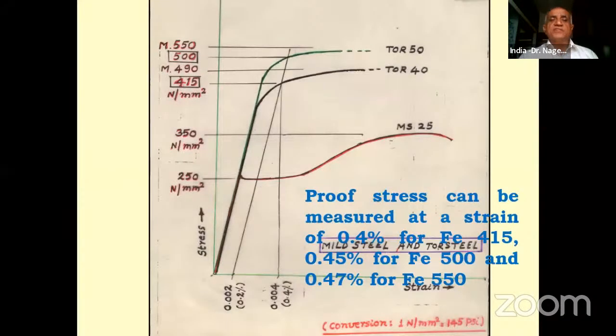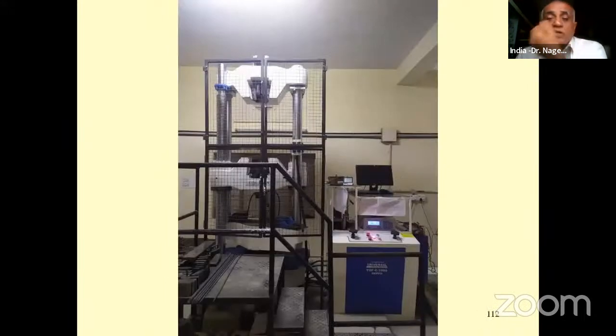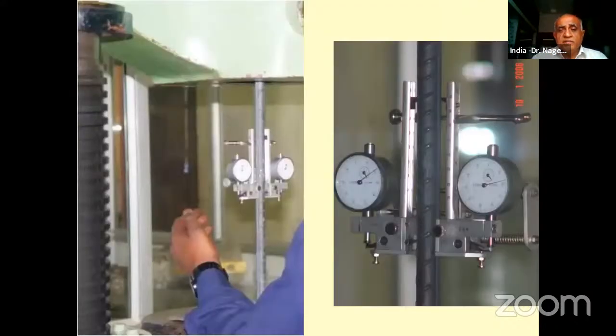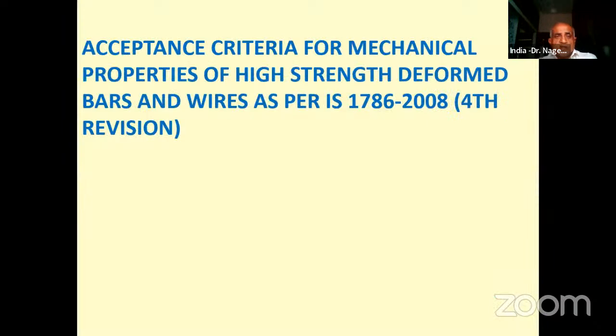See, these are the graphs we plot for the stress strain, and this is a universal testing machine where the steel bars are tested, with a mechanical extensometer. Nowadays we have electronic extensometer. This is a mechanical extensometer being fixed onto the steel specimen. And a typical failure will look like this. You can see there is a cup and cone fracture happening, because it is a TMT bar, like mild steel only.